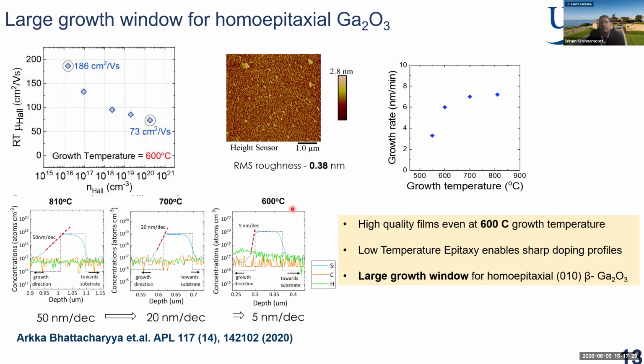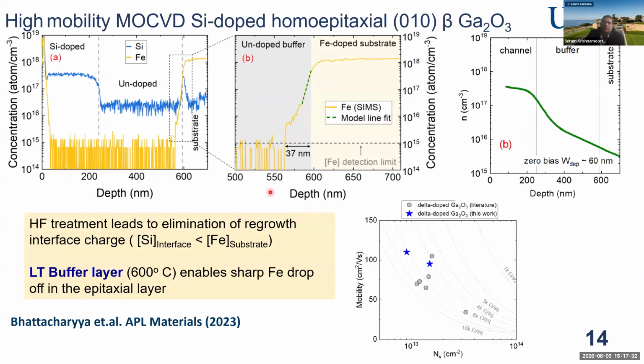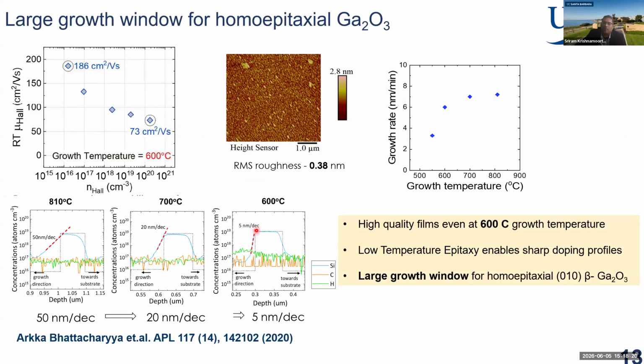This can be used to our advantage in terms of growing these materials on substrates. Typically we grow on insulating substrates, doped with iron as the compensating dopant. And this iron in the substrate can actually get into the epitaxial layer. Being able to grow a low temperature initial layer or nucleation layer on gallium oxide can help us really drop off the iron surface riding into the film to within tens of nanometers close to the substrate. Then once we do the low temperature layer, we can ramp up the reactor temperature and grow high quality doped layers. So having this large growth window for this material system is quite exciting, and it helps us get sharp doping profiles.